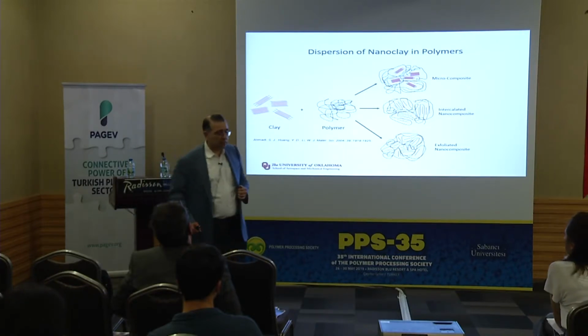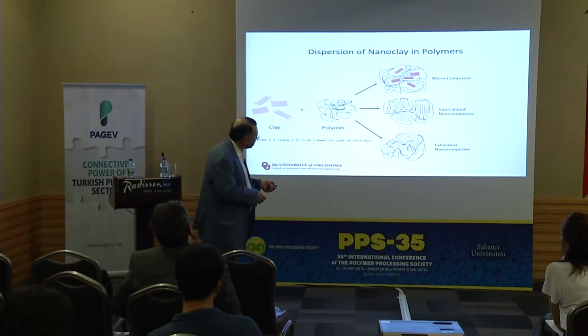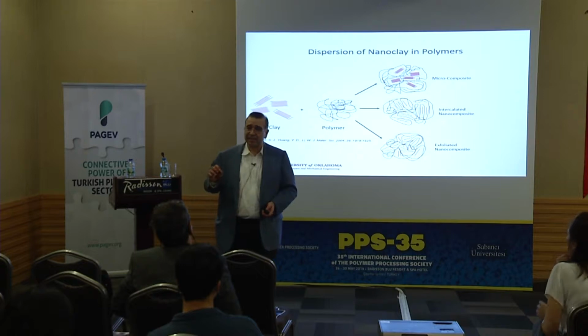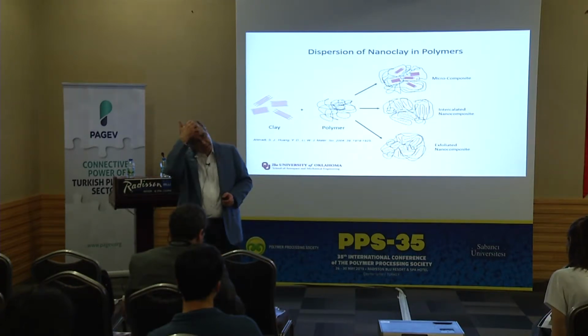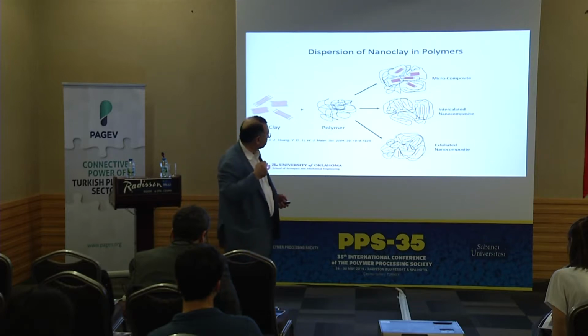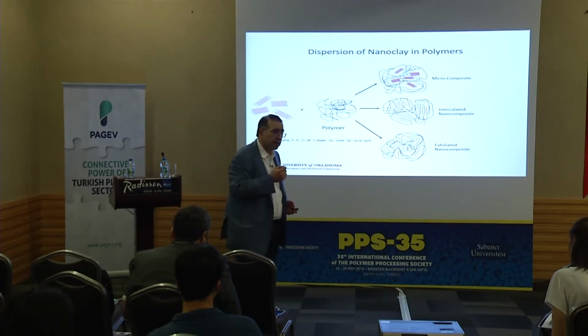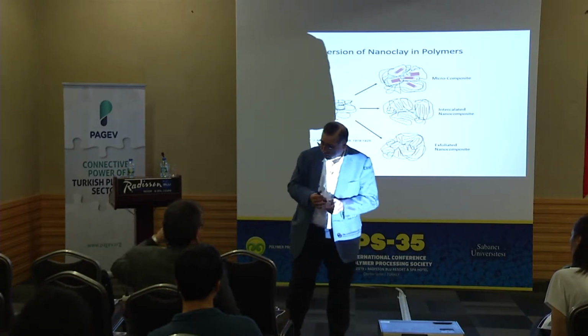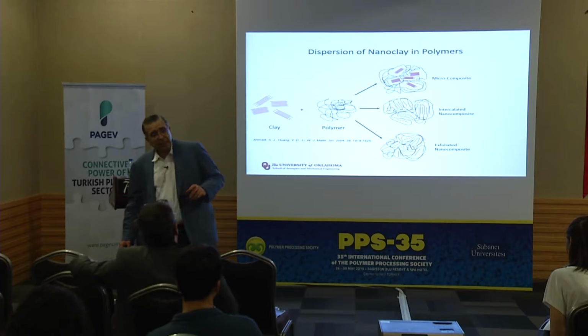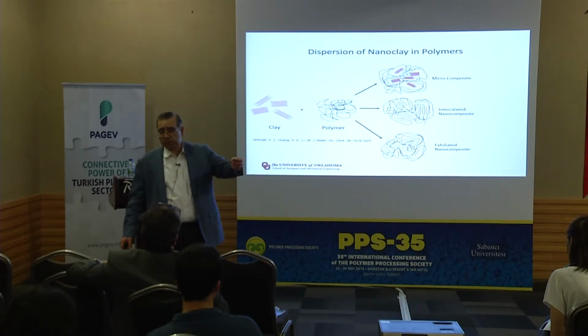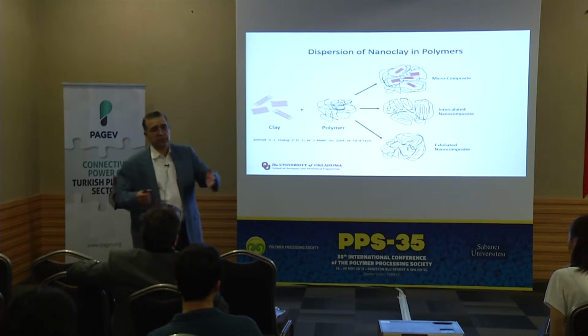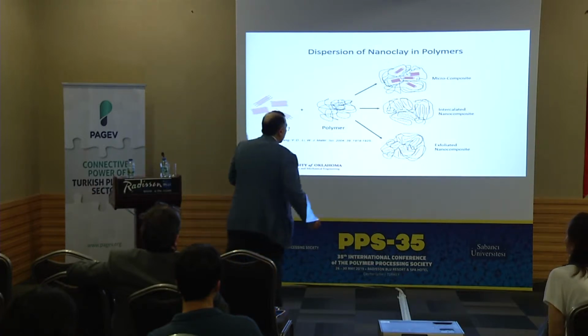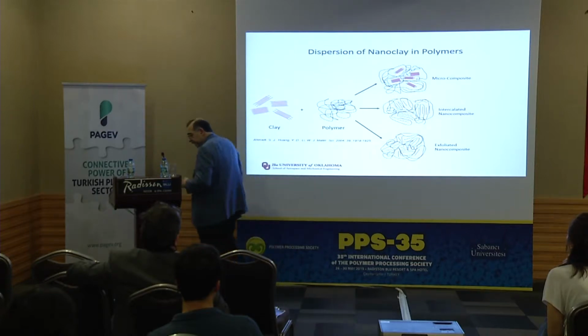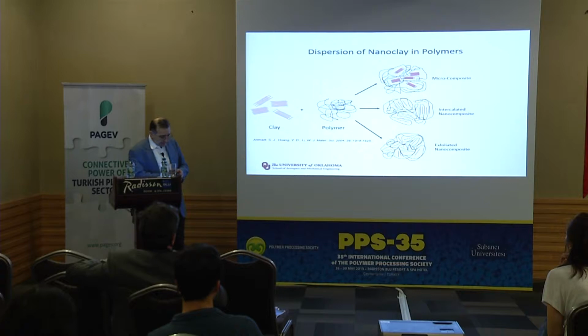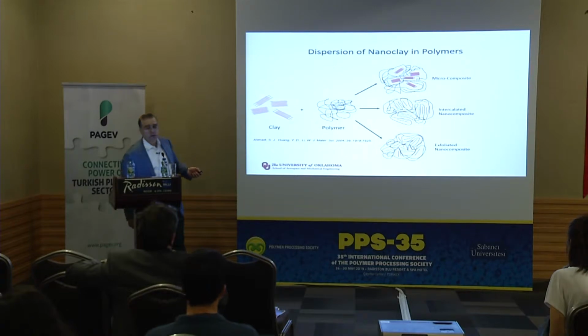And what people do is observe these things under TEM. SEM will not really show you whether you have intercalation or exfoliation, but using TEM, the transmission electron microscope, you need to section the sample very thin and look at the platelets. But that's a very small area, and maybe 1-2 samples. You really do not know how the entire part or product is. Very likely, you will have a combination of exfoliated regions, some intercalated, and a lot of microclusters.